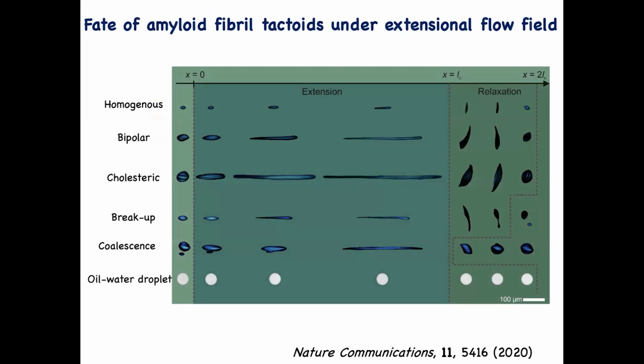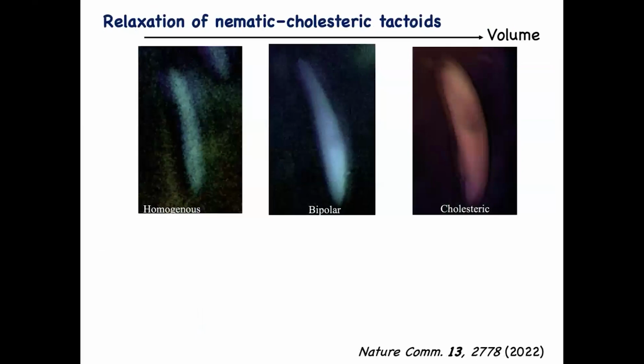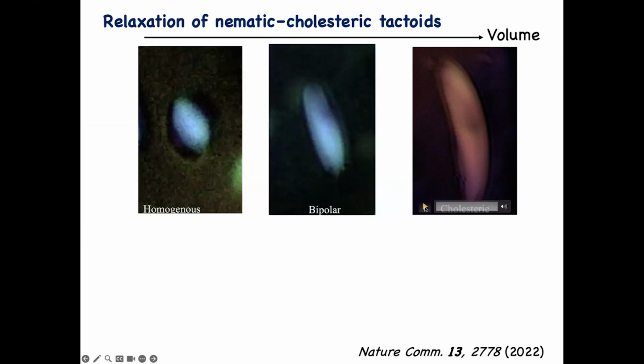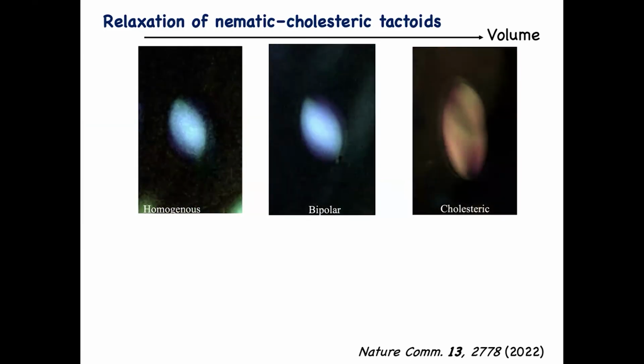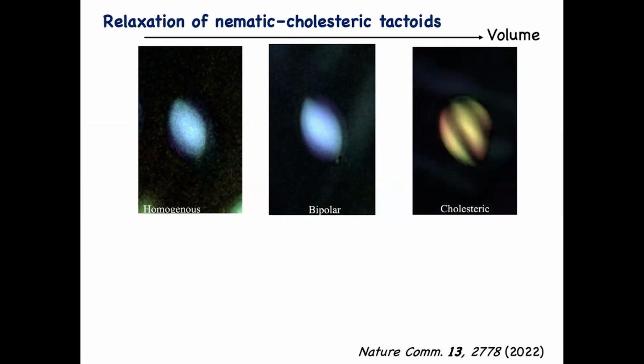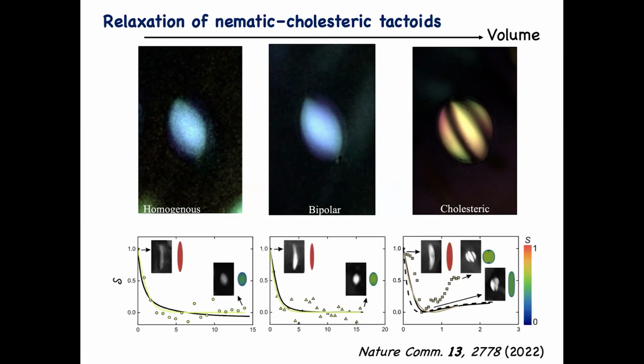And look, this is an oil-water droplet in the same channel, it just goes totally unperturbed. So this really distinguishes an extremely small surface energy. And of course, the interesting part is not only when they stretch, also when they relax. These are movies that I am trying to display now. We're looking now at the droplets that are relaxing after they have left the channel. And you see they recovered the original symmetry, including the cholesteric. And now you can follow how the order parameter evolves. So this is very interesting.